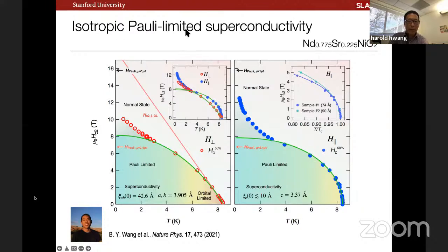The title is kind of the bottom line story. It's interesting because it looks unusually isotropic in terms of Hc2, and it roughly corresponds to Pauli-limited superconductivity. The point I was just going to say is that if we put the magnetic field in the plane direction, this is how Hc2 looks. The point is that this looks like it's Pauli-limited, but with an enhanced moment, if you will. If I just put that in by hand, it gives you about 2.5 Bohr magnetons.